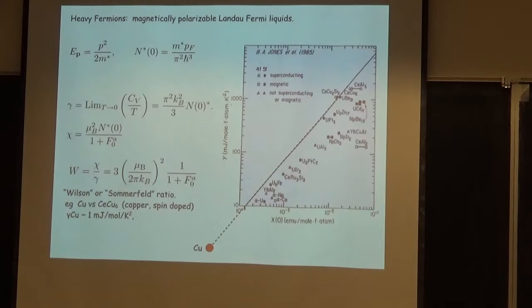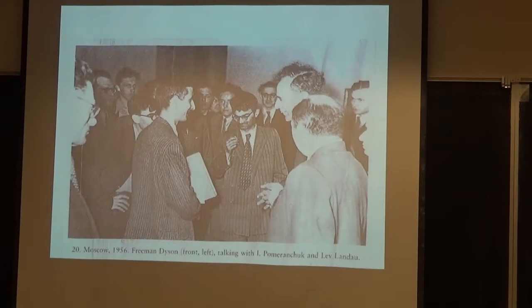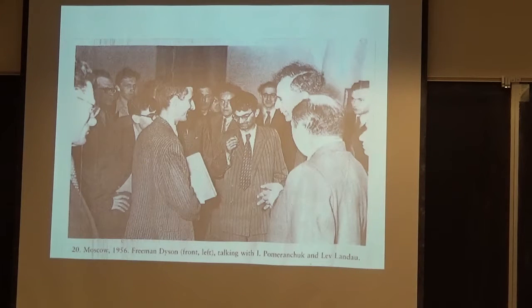And it's rather interesting to compare copper with a little bit of cerium in it, known as cerium copper 6. Copper is somewhere down here, has a gamma of about 1 millijoule per mole Kelvin squared. And if you look up here is cerium copper 6 up there, and it has a gamma of around 1,000 millijoules per mole Kelvin squared. And so on the basis of this, the mass renormalization determined by the density of states is about 1,000. Some of that effective mass comes from band theory, probably a factor of 20, and that comes from band theory. But the remainder comes from interaction effects. And so it's rather remarkable that you can actually increase the mass by a factor of 20 or 1,000 or who knows what, and that the system is still a Landau Fermi liquid.